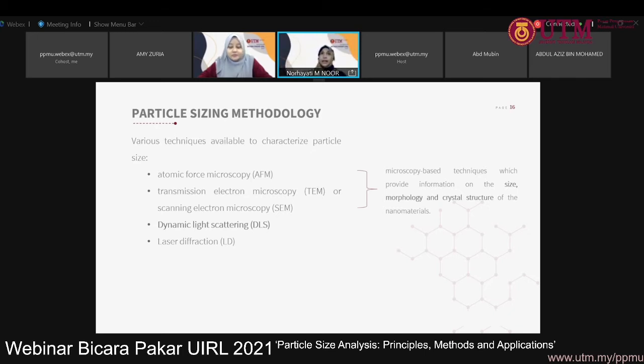So when you do particle size measurements using DLS or laser diffraction, you have to do another additional measurement, for example TEM. In my study, normally when we check the size of particles, we get the hydrodynamic diameter and the distribution, and then we confirm with TEM, transmission electron microscopy, so that we know that this size of particles is not really far from the TEM result. When the results are far different from each other, then you know how your particles behave. Sometimes the size in DLS is smaller than the morphology from the TEM, and sometimes you get a bigger size, and then you can know how your particles behave. Okay.